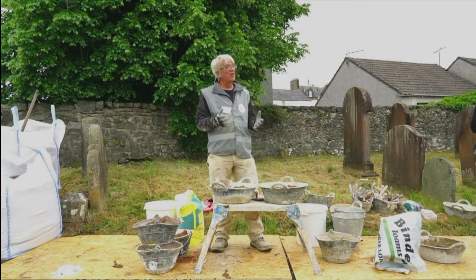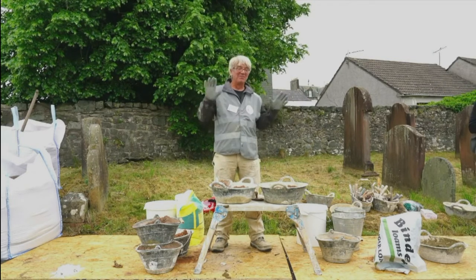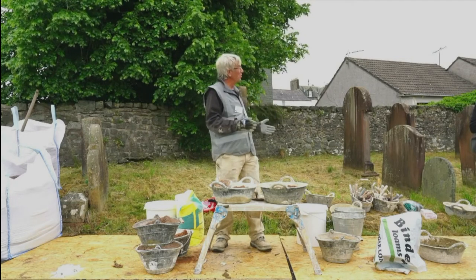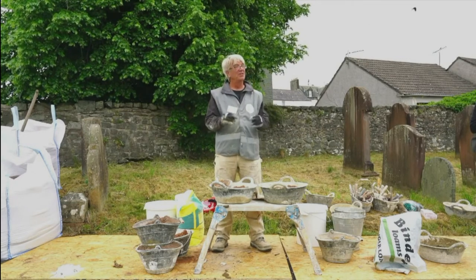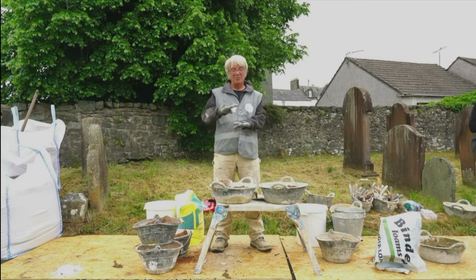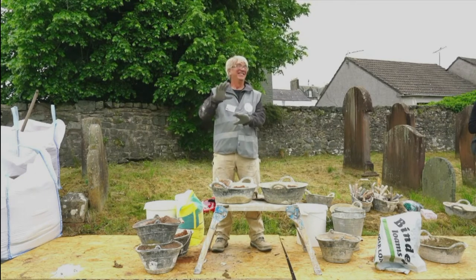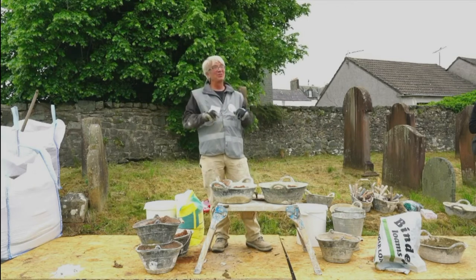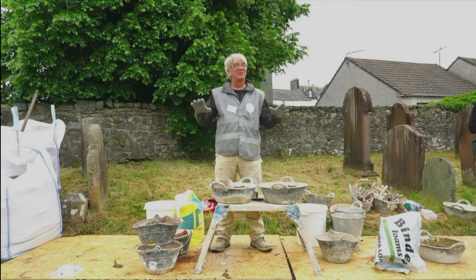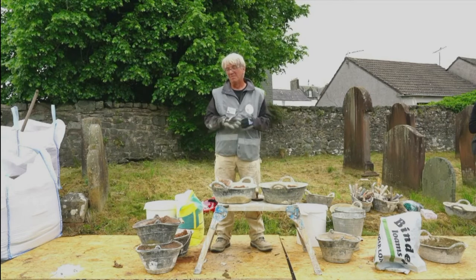Hot mixes stiffen very easily, very readily. If you were building a flint wall, for instance, or a wall with cobbles, I've seen the specs for doing that with lime putty mortars. You build two courses and then you leave it for a couple of weeks and you go back and you build another couple of courses. Because if you try and go any further with an impermeable stone, they'll start to swim around and you lose control and they're losing place and so on.